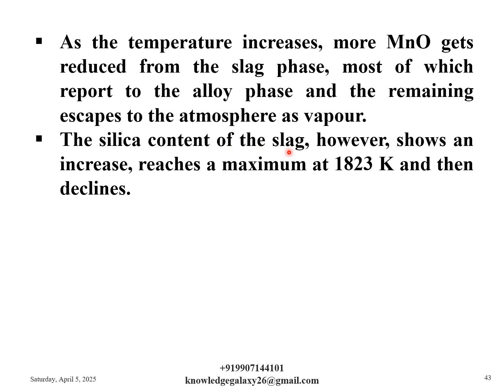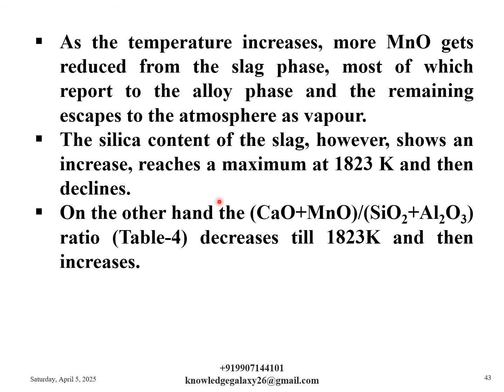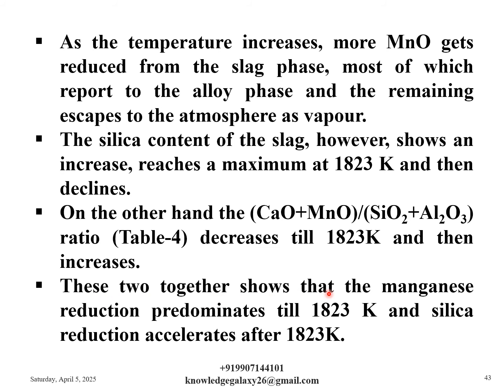The silica content of the slag, however, shows an increase, reaches a maximum at 1823 Kelvin and then declines. On the other hand, the CaO plus MnO divided by SiO2 plus Al2O3 ratio, which is given in table 4, decreases till 1823 Kelvin and then increases. These two together show that manganese reduction predominates till 1823 Kelvin and silica reduction accelerates after 1823 Kelvin.